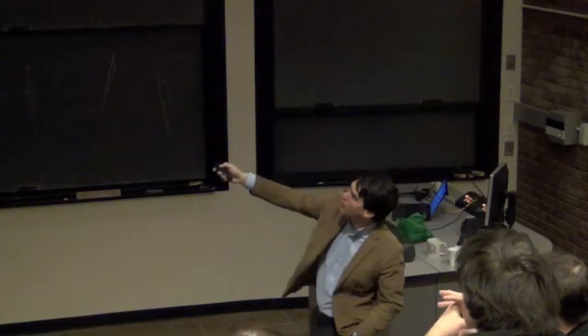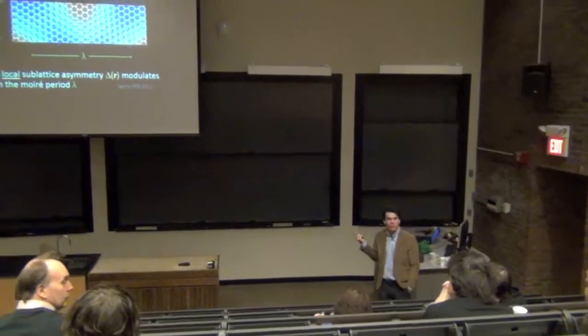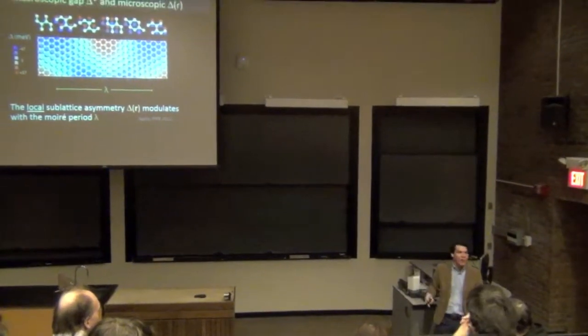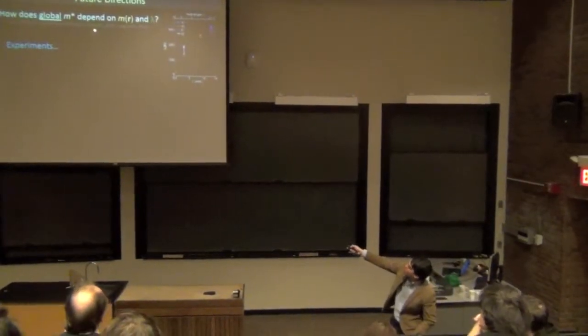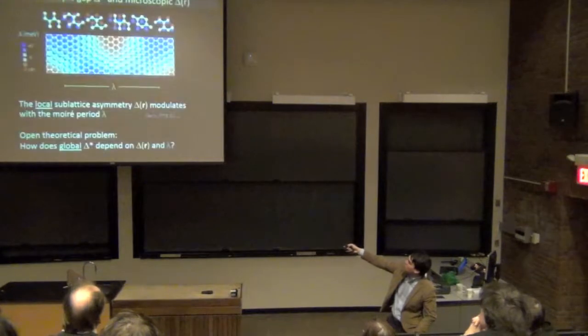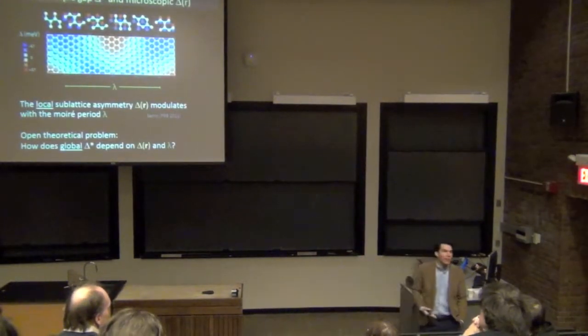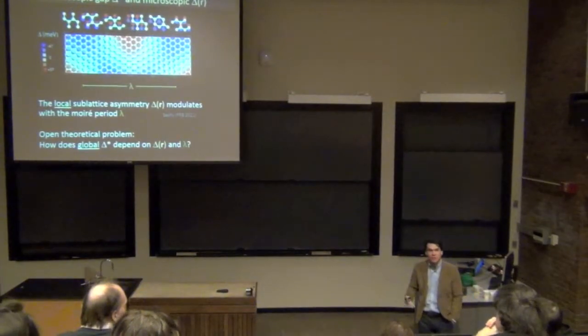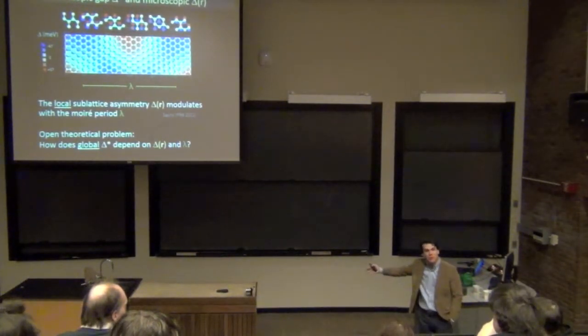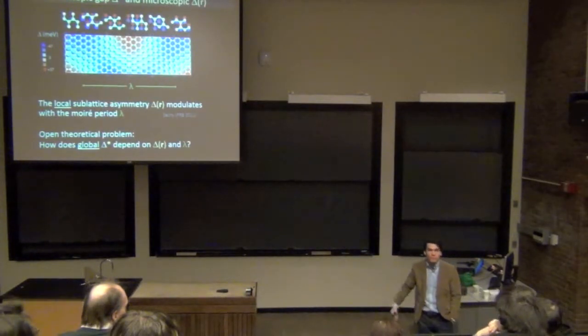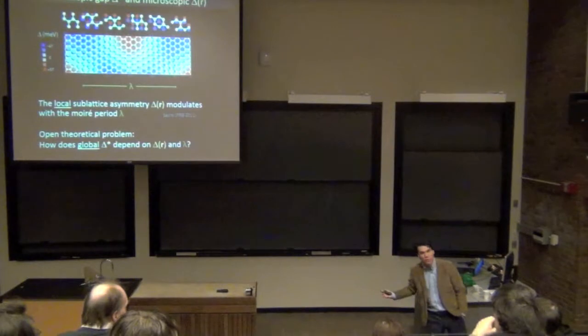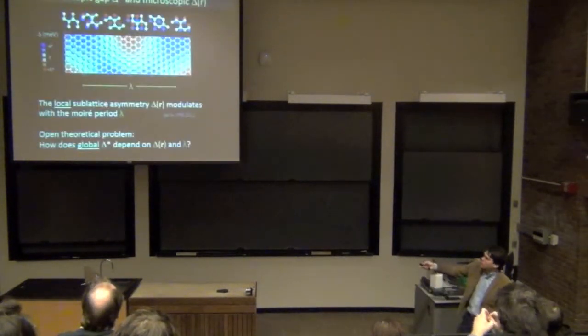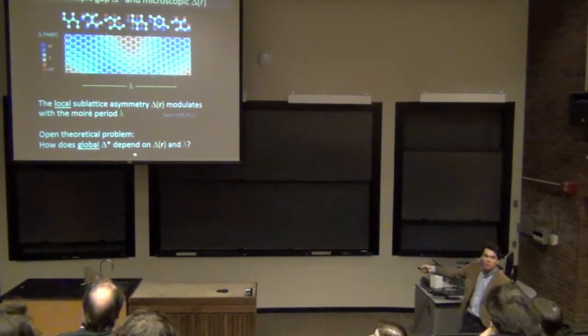Yeah, exactly. That was Bruno's paper actually. In first order, the gap should average to zero over the whole sample. In third order, it doesn't. And there are some ideas from Lenz and Levitov, for example this paper from Song et al., that talks about how the Fermi velocity and the microscopic mass term are renormalized and can actually become quite significant at macroscopic length scales much longer than the moiré. So that's what I meant about this being the open theoretical problem: exactly how this depends on that.